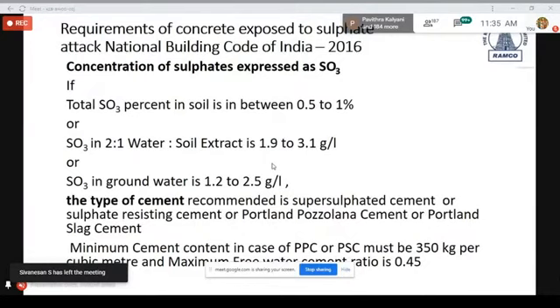And the minimum cement content in case of PPC or PSC, you will have to use 350 kg per cubic meter, and the maximum free water cement ratio is 0.45 if it has to resist the attack of sulfates. So it is very important to bear in mind that if you have this much percentage of sulfate expressed as SO3 in soil or in groundwater, you can safely go for blended cements and do not jump to the conclusion that you have to use SRC cement. This is very clearly mentioned in IS 456 2000. There is a tabular column that says what you should do, and that is where you can use blended cement for resisting the attack of sulfate as well as chloride.